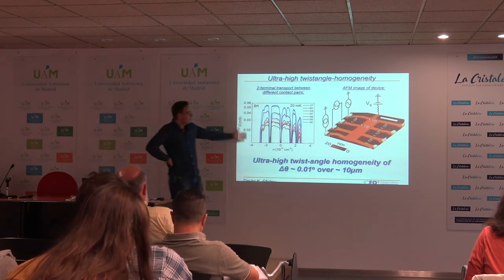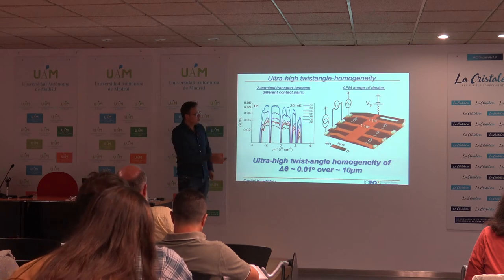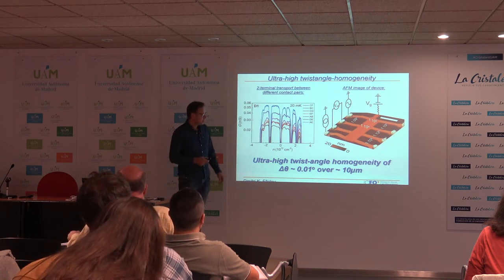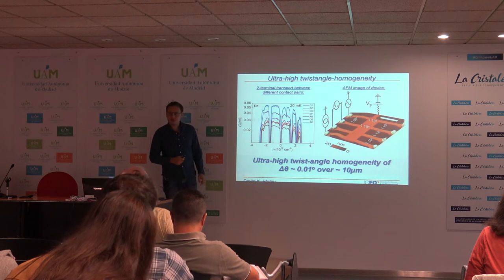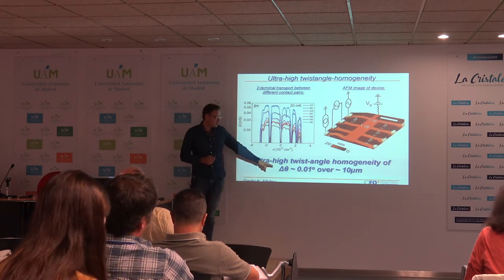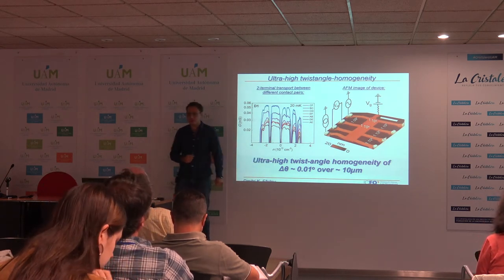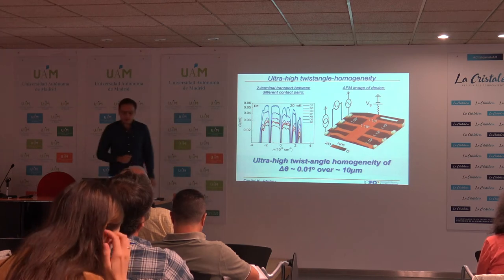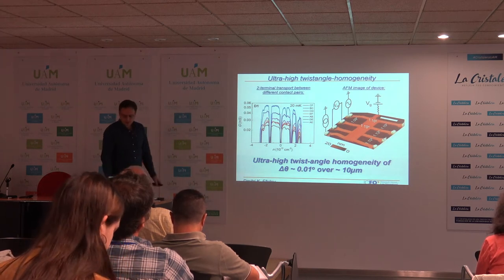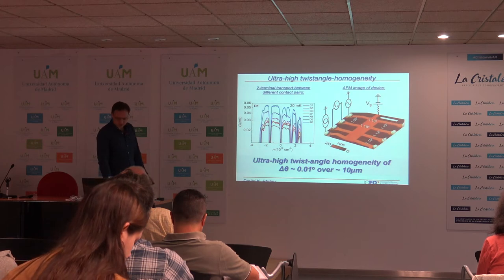And so we can perform these measurements in all different regions of the device, and we really find that the twist angle homogeneity of our device is extremely good. So we have a variation of less than 0.01 degrees over about 10 microns. And as far as we understand, these are really the cleanest devices out there right now.